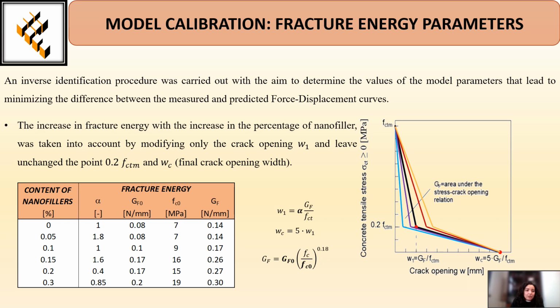For the calibration, an inverse identification procedure was carried out with the aim to determine the value of the model parameters that lead to minimize the difference between the measured and predicted force displacement curves. In particular, the increase in the fracture energy with the increase in the percentage of nanofiller was taken into account by modifying only the crack opening w1 through the alpha parameters, but also the fracture energy through the initial fracture energy and the initial compressive strength.